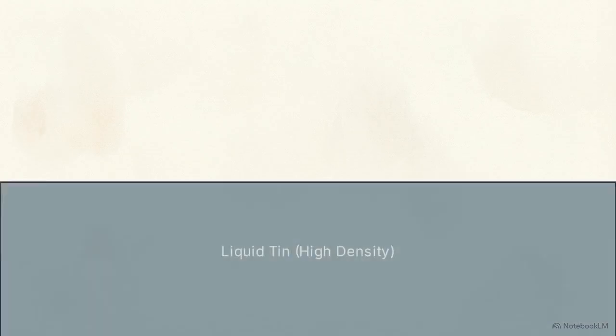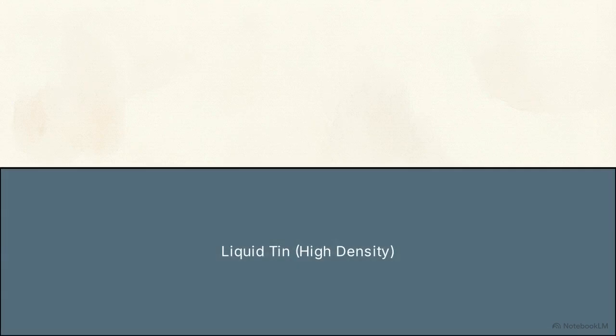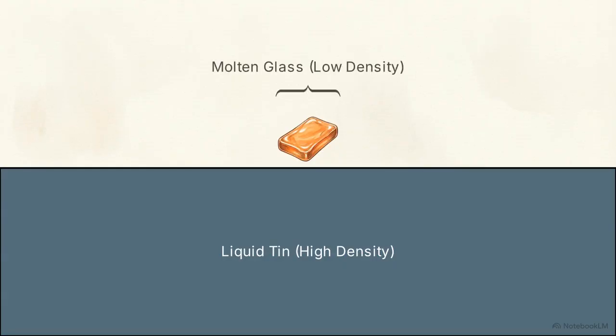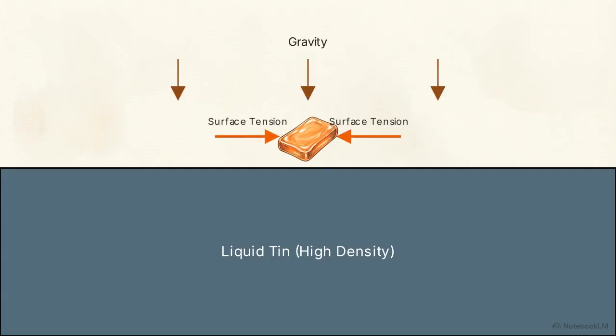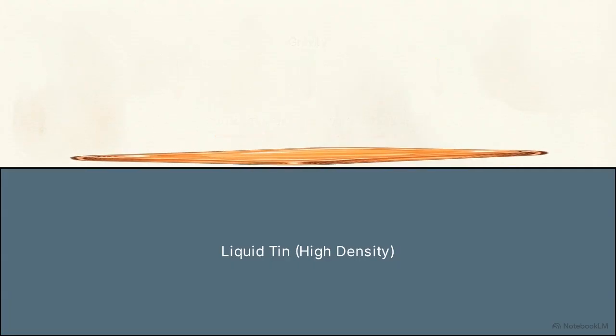Here is a diagram showing the core physical mechanism Pilkington designed. The molten glass is poured directly onto a highly dense bath of liquid molten tin. Because the glass is less dense, it floats right on top. Gravity and surface tension take over. The glass spreads naturally across the liquid metal, exactly like oil floating on water. This creates an absolutely flat surface where the upper and lower boundaries remain perfectly parallel.